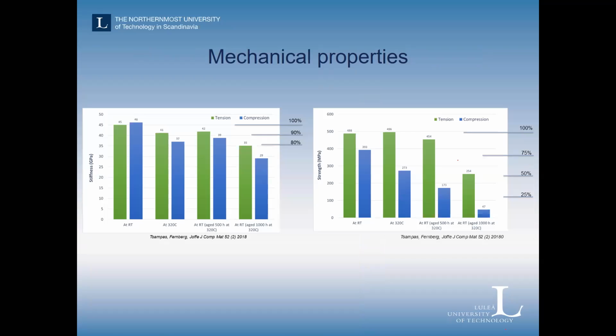So when looking at the mechanical properties, we have also done that, of course. We have done tests at different environments. The green bars here are measurements for tension, and the left graph is stiffness for different cases, and the right graph is strength. The green bars are always tension. The leftmost pair are at room temperature. These are the properties we measure at room temperature.